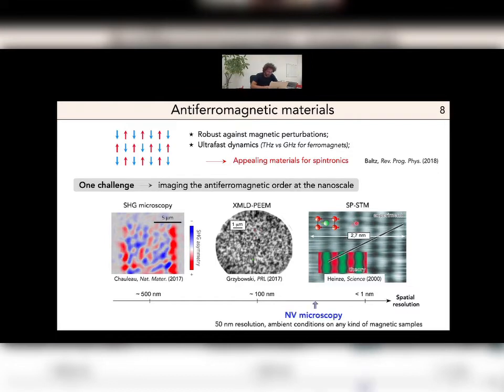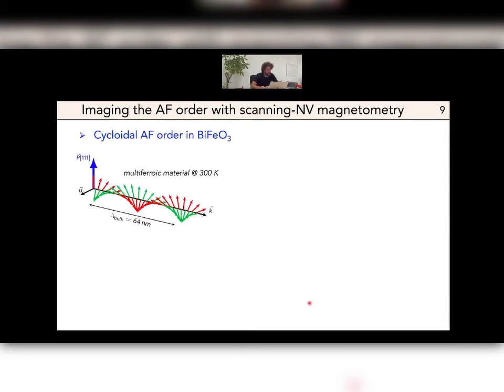In our case, we will use NV microscopy, as I told you. The spatial resolution is in the range of 50 nanometers, and the key point is that it is a tabletop experiment that can be used in ambient conditions on any kind of magnetic sample. In the last years, we have used this NV magnetometer to study antiferromagnets, and one of our focuses was a well-known multiferroic material, bismuth ferrite, which is both ferroelectric and antiferromagnetic at room temperature.